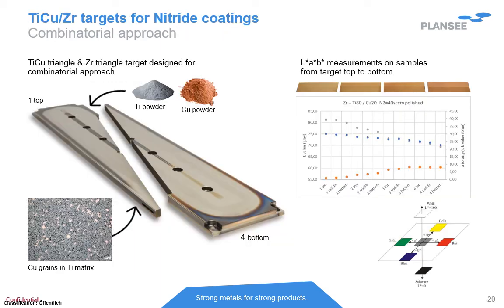The next case I would like to talk about is related to nitride-based decorative coatings. In order to screen the big variety of possibilities in one experiment, it seems to be useful to work with a combinatorial approach, shown as a target on the left side. In this case, we applied a titanium-copper target in combination with a pure zirconium target to screen the whole titanium-copper-zirconium system. In front of such a target, several substrate samples were placed.